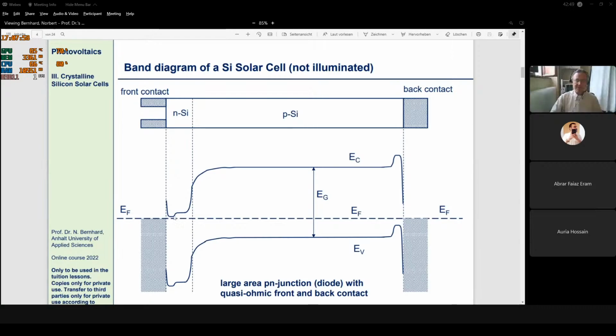That means usually a metal to a semiconductor forms a Schottky barrier, which in principle would be a Schottky diode. But of course, we don't want a Schottky diode here. We just want metal contacts, and this is the reason why we dope it very highly. That means directly at the contacts, the semiconductor material is so highly doped that the Schottky barrier becomes very narrow. And that means the charge carrier can tunnel through it. I mean, classically it's forbidden, but quantum mechanically it's possible.